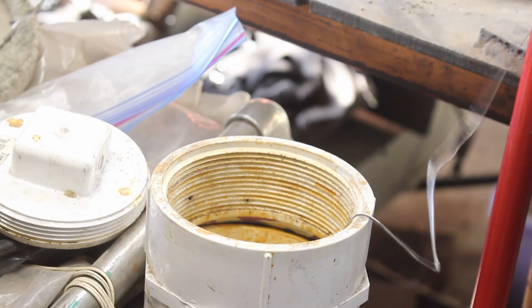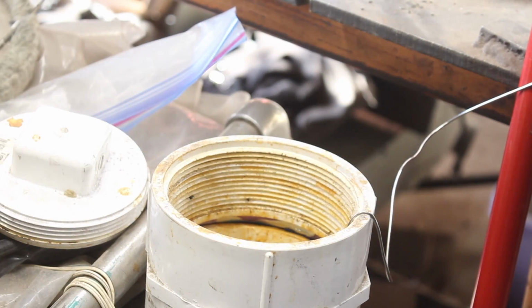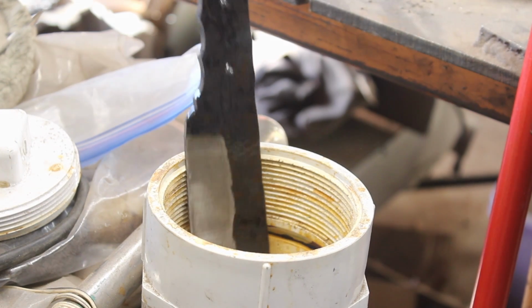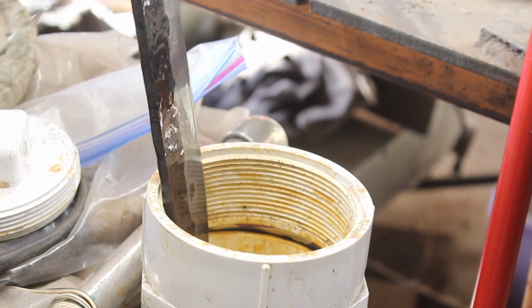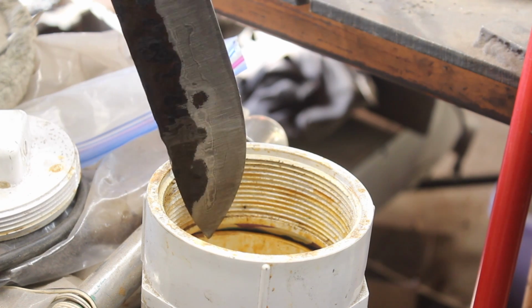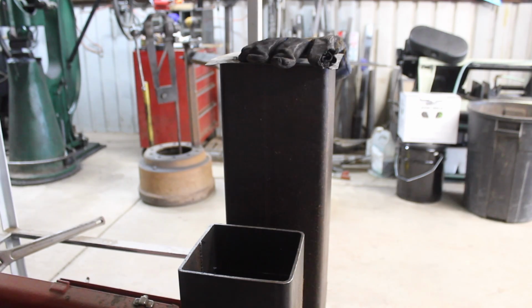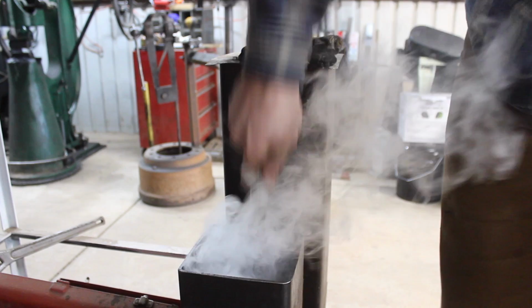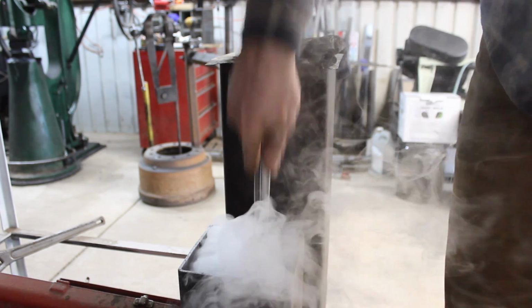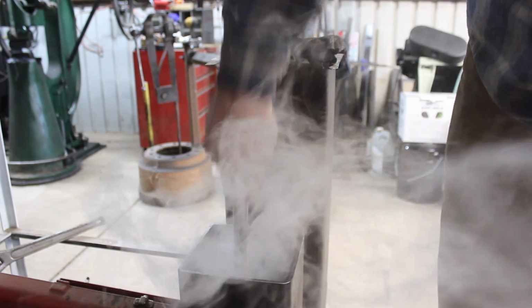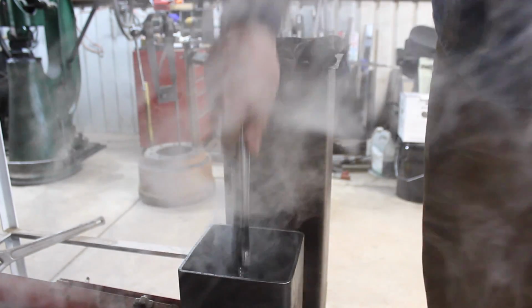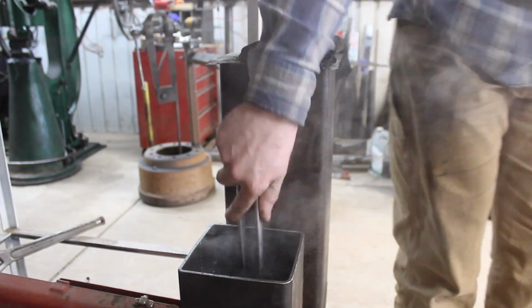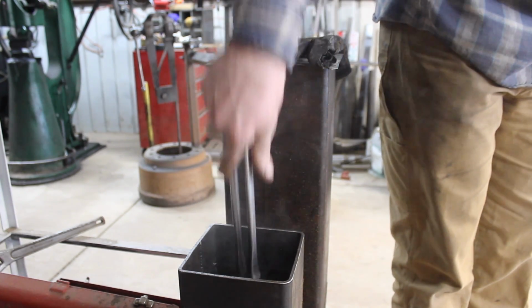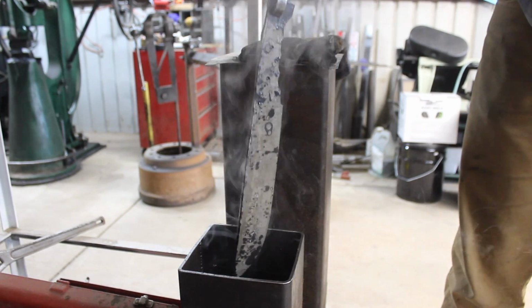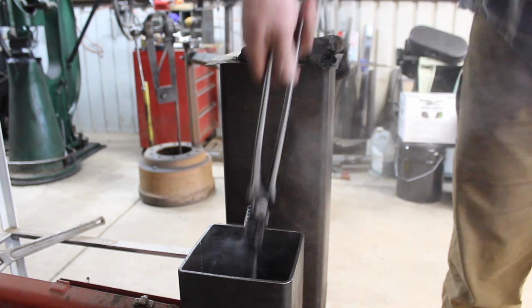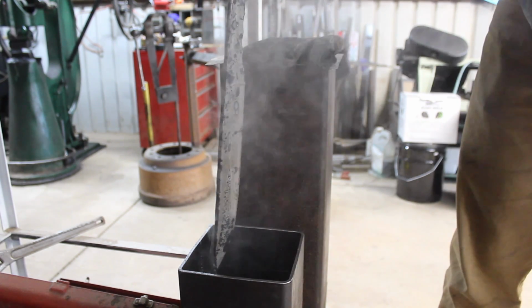I'm using a quick ferric chloride etch. It's kind of worn out, it's not doing so good, but it's just enough to tell me where my edge steel is, and then I can adjust my grind accordingly so that we're on track to where we need to be on the finished grind of the blade. And then I can go ahead and harden it. You saw me rough grind the blade. That's not absolutely necessary, but again, why grind hardened steel any more than I have to? That also helps me make sure that my San Mai is centered. So now we have a nice hardened blade, and we can make sure that it's straight and get it tempered.